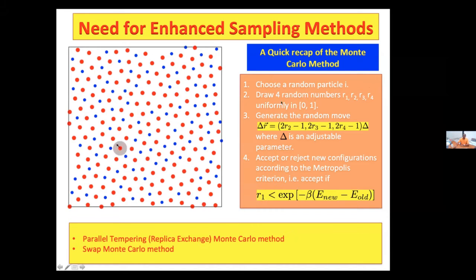You choose a random particle, you draw 4 random numbers between 0 and 1 and generate a random move, which is given by this delta R. And the delta is an adjustable parameter. You tune it such that your acceptance probability is around 50%. And then you accept this next move according to this Metropolis algorithm given by this. So in this cartoon, what I'm showing you by the shaded area is that one random particle is chosen. And then all of these steps are checked. And whenever the moves are accepted by the Metropolis criteria, then I move that particle. So this is what a simple Monte Carlo method is.